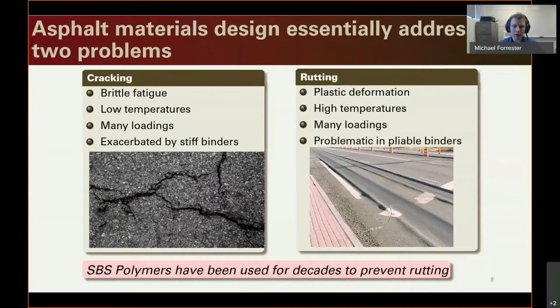In the cracking, what happens is that at low temperatures, and with frequent loading of the vehicles driving across the pavement, you get these cracks to form, and that's what leads to things like potholes and issues with cars driving over them. Likewise, you have issues with rutting in high temperature environments where you end up with a lot of load on the road, and the pavement starts to basically flow. What the polymers do is they help to dissipate some of the energy in the cracking mode, and they also help to provide some elasticity in the rutting mode. So the pavement will still deform to a degree, but it'll come back to where it originally was.